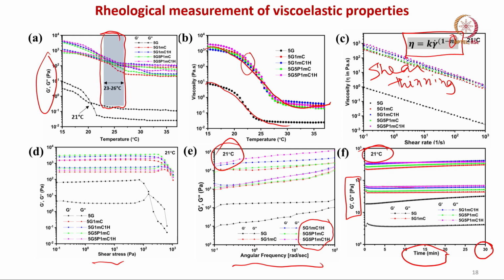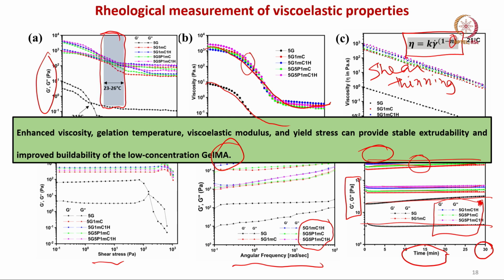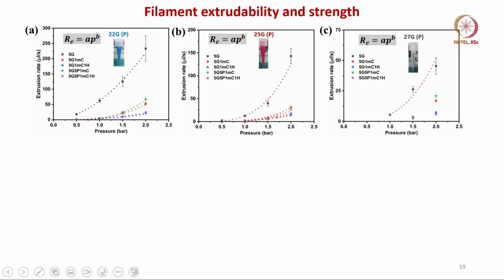Indeed, you see that there is no variation with temperature, right. There is no significant variation, and you can see different groups of data shown, like G prime and G double prime, for the different hydrogel matrices. So, enhanced viscosity, gelation temperature, and viscoelastic yield stress can provide stable extrudability and improved buildability of a low concentration of gelatin methacrylate, GelMA, that is 5% GelMA.